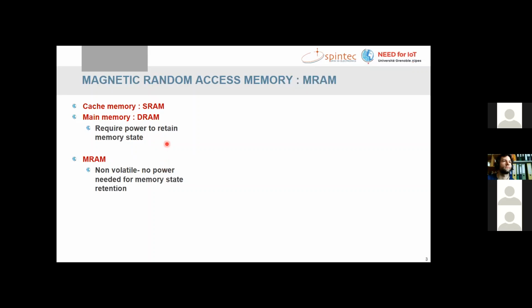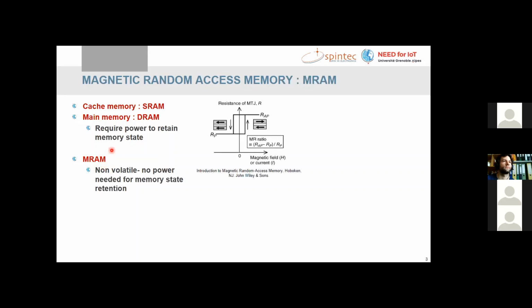To make a comment, he mentioned that the ferroelectric RAM was very good in terms of retention, but actually MRAM has even higher retention capabilities. So it is really expected to play a very important role in the future. Just to show you a little bit how this type of memory works: we have two magnetic layers separated by an oxide barrier, and depending on the orientation of the two magnetic layers, we can have a low resistance state or a high resistance state. This is what defines the bit for information storage.